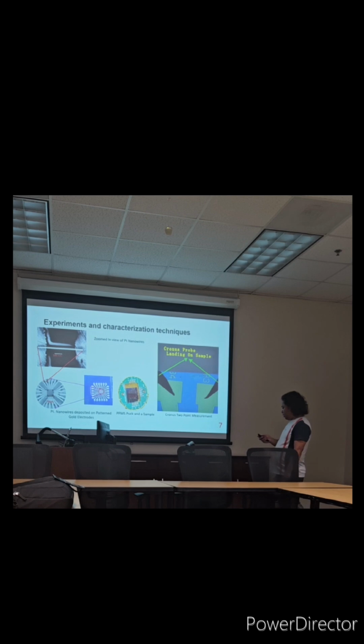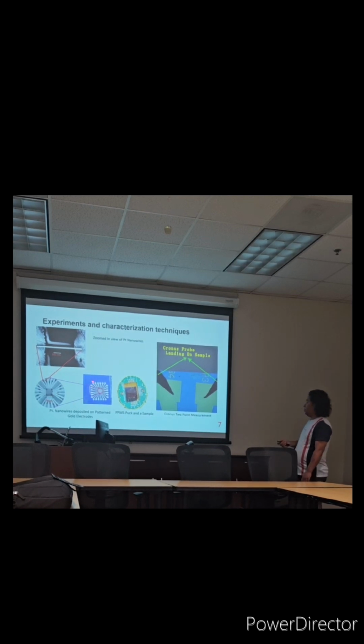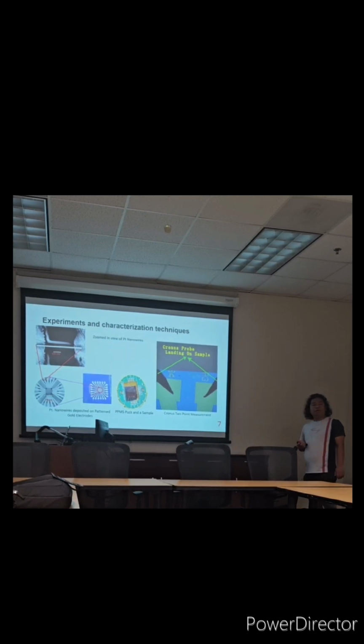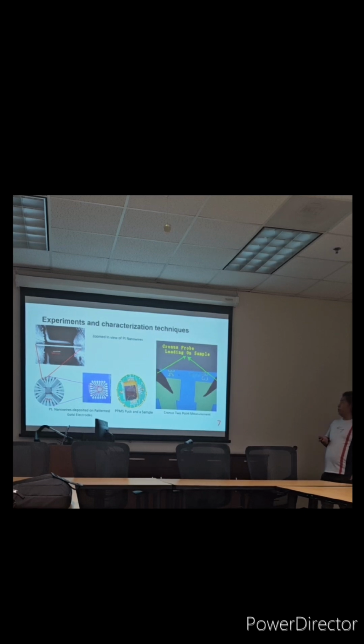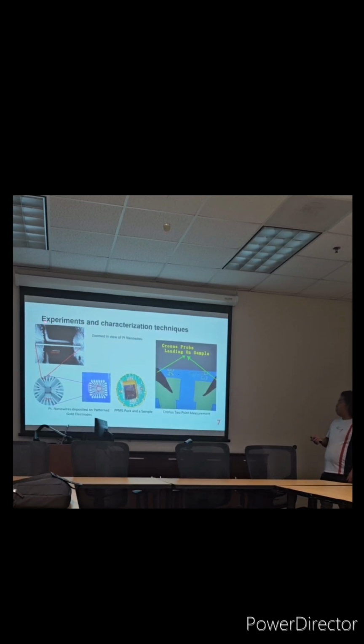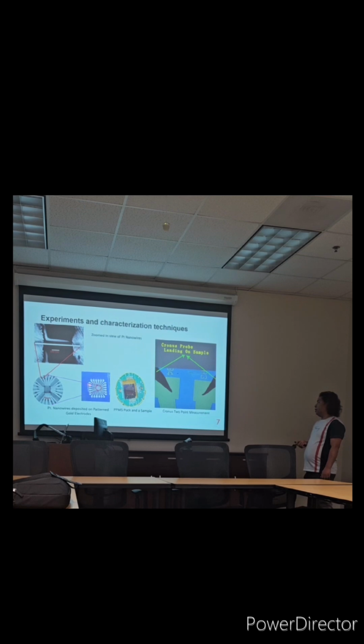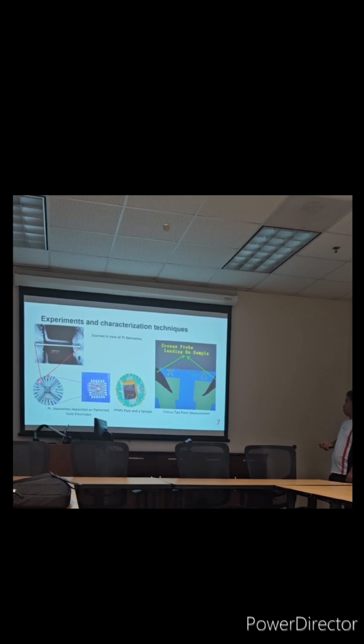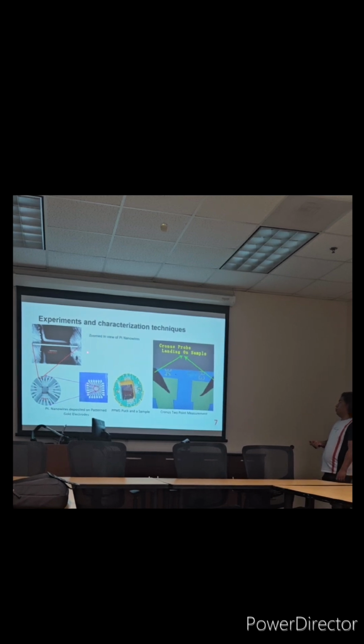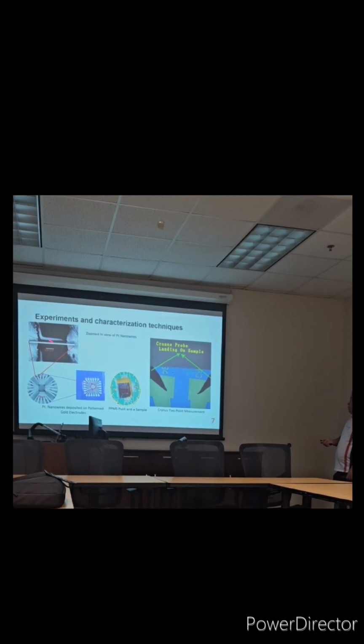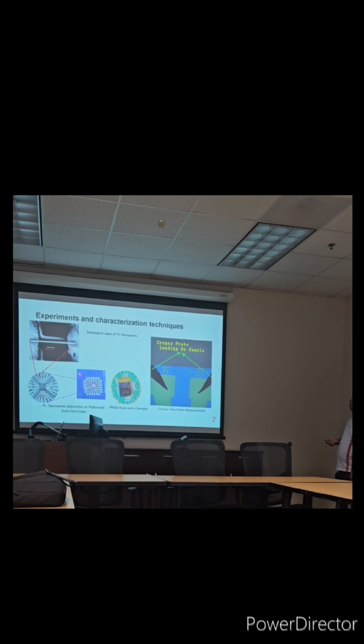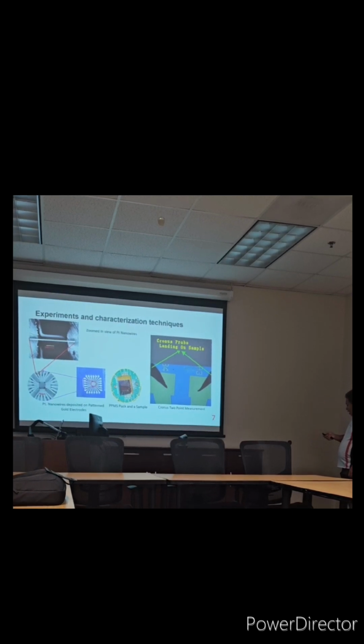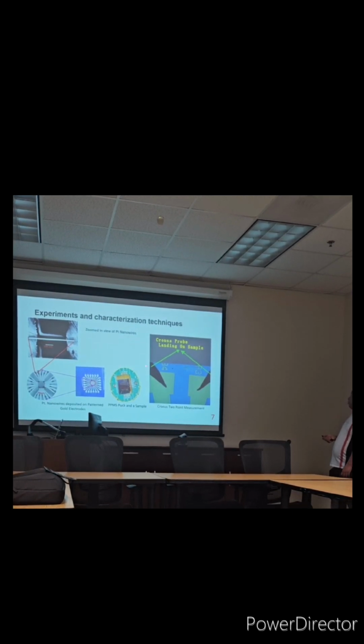This slide shows a sample on the bottom left prepared by Ujjwal using electron beam lithography technique. Platinum nanowires are deposited to connect these adjacent electrodes. The SEM micrograph here shows a number of black spots. A zoomed in view shows the deposited platinum nanowires. On the right, you see 2 black probes of the probe station being landed on the electrodes. It's ready for IV measurements.